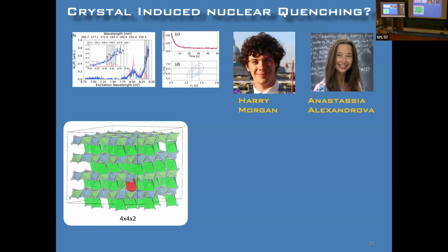So this is the number of unit cells of our crystal. This is LiSAF, so it's 4 by 4 by 2 unit cells. There's roughly infinity electrons in this calculation. And right here, one of the strontiums has been replaced with a thorium. The reason you have to do this is these calculations often have periodic boundary conditions, so if you just do 1 unit cell, then there's thorium everywhere, and the structure will be different. This is like the limit of what they could do on supercomputers, but it appeared to be converged. As you go to smaller, the results don't really change.